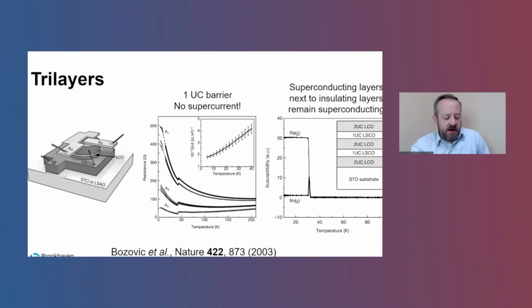Heterostructures of the opposite configuration, in the graph here on the right, where a single unit cell of optimally doped LSCO was sandwiched between thicker layers of insulating LCO, confirmed that the superconductivity in the LSCO was not somehow killed by the LCO, artificially increasing the thickness of that insulating barrier. So this tiny layer really is a very effective barrier against transmission of supercurrent from one side to the other. We recently revisited this SIS geometry, not really expecting that these junctions would act as Josephson type junctions, but more like a normal tunnel junction, since clearly from that middle graph not all the current was expected to be blocked.